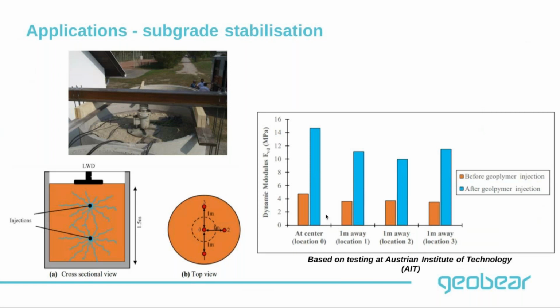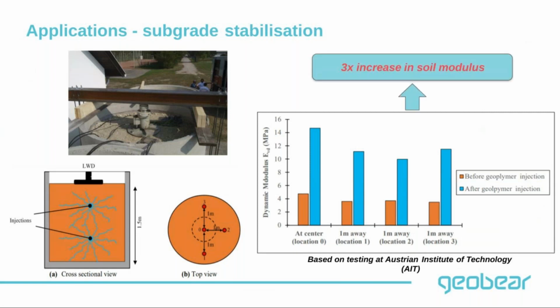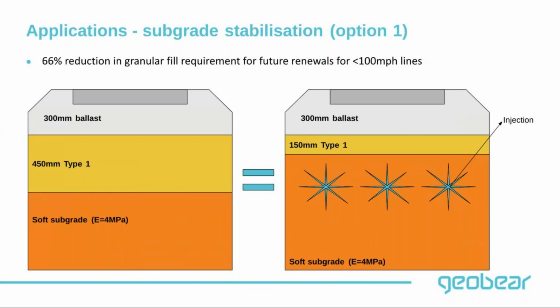Before the injections, we measured in various locations, and we had an average stiffness value of around 4 MPa. But after the injections, we managed to increase the soil modulus by almost a factor of 3, to almost 12. So that's quite an impressive increase in the stiffness of the soil just by doing the injections. If you take these improvement factors that you've witnessed in the test, we can easily apply that in a track renewal.